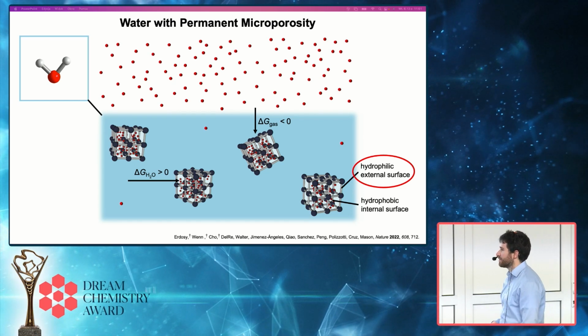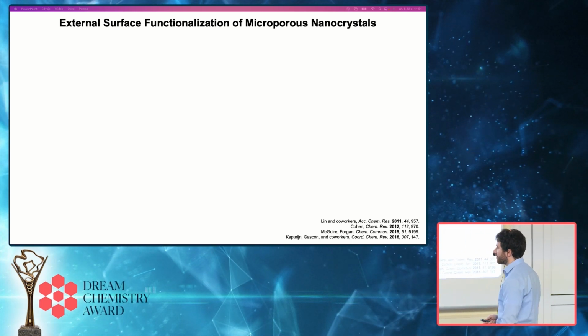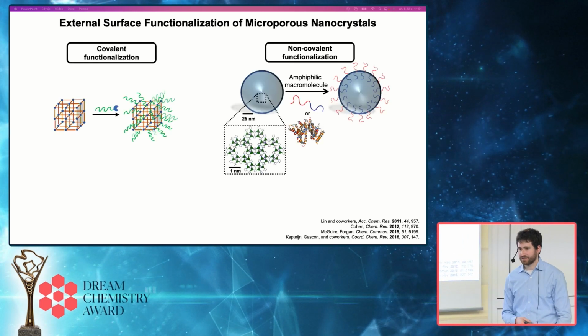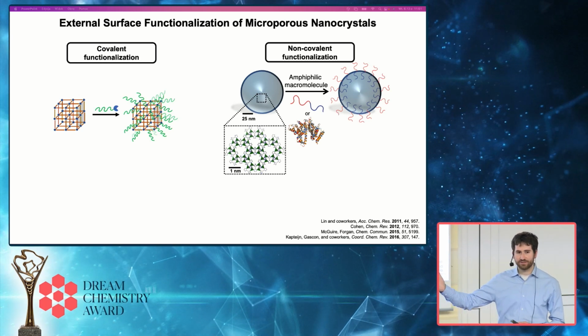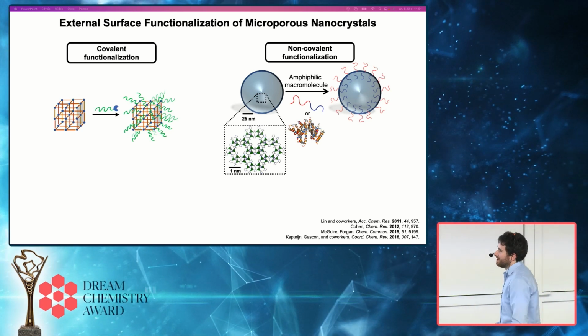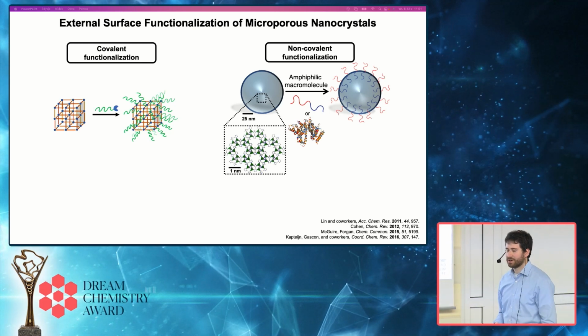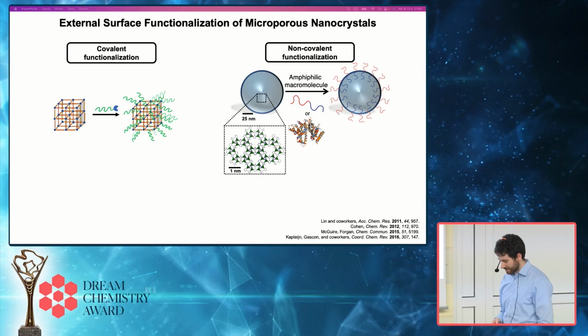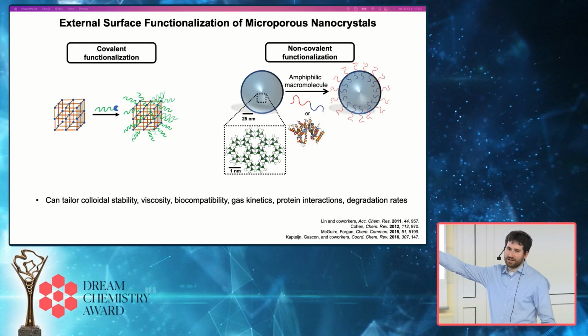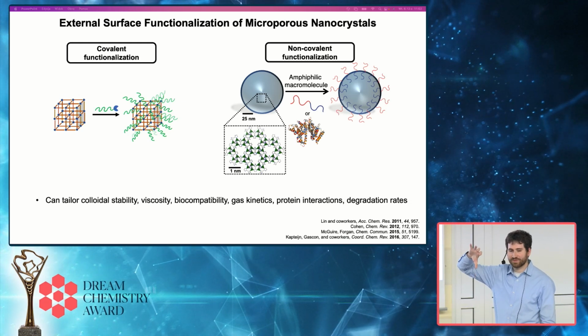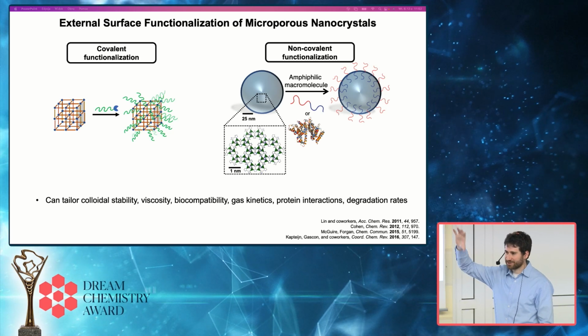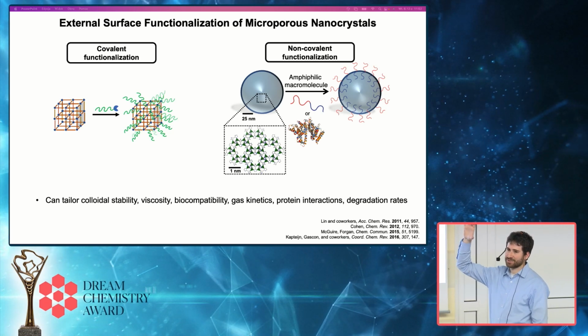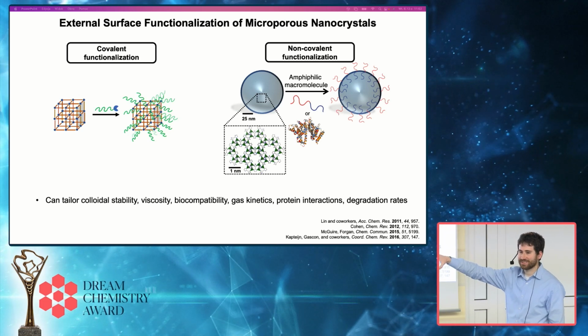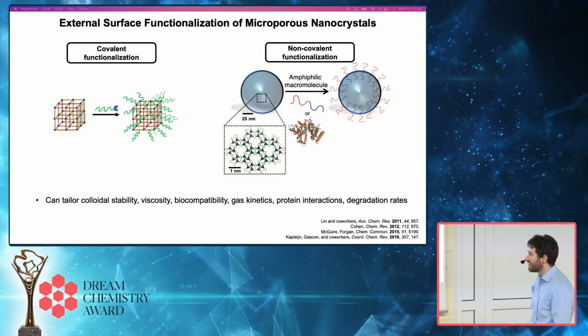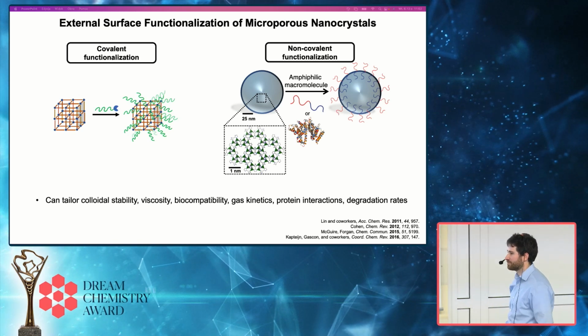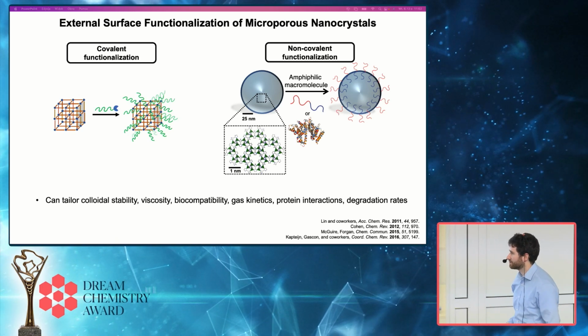And so we spent a lot of time over the last 1 to 2 years developing ways of selectively functionalizing the external surface of metal organic framework nanoparticles to make those surfaces hydrophilic. One of the challenges in doing that is that you need to be able to put surface ligands on the external surface of a porous material without blocking access of gas molecules to the internal pores. And you need to make sure those surface ligands don't go inside your pores and remove all of your porosity. Doing that can be quite challenging, but there's a couple of different approaches that one can take, some of which were alluded to by Carl.